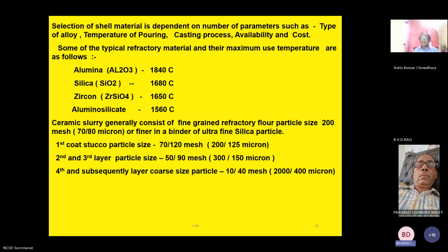Ceramic slurry generally consists of fine-grained refractory flour, particle size 200 mesh, that means 70 to 80 micron, or finer, in a binder of ultra-fine silica particles. First layer particle is 70 to 120 mesh, 200 to 125 micron. Second and third layer is 50 to 90. And the fourth and subsequent layers have a particle size of 10 to 40 mesh.